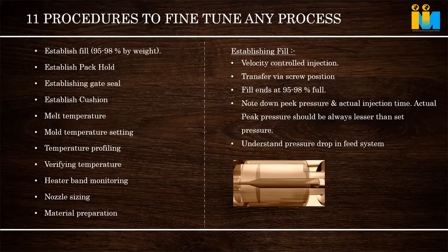If my gate is small and freezes, whatever amount of holding I give will not go into the part. The part will have shrinkage or sink marks, even though we are giving huge pressure, because nothing is going inside the cavity. So holding also has to be established properly, and the gate freezing time should be kept in mind.